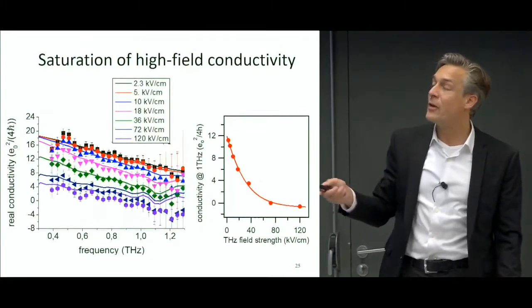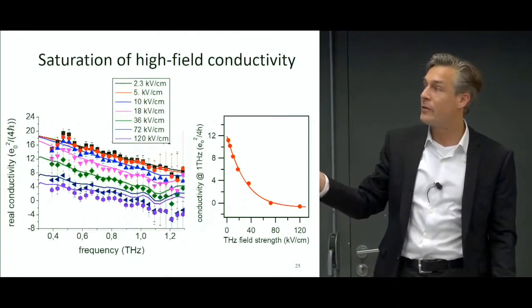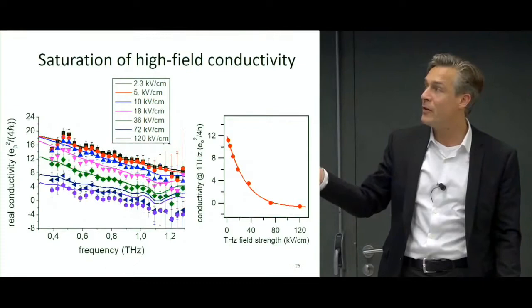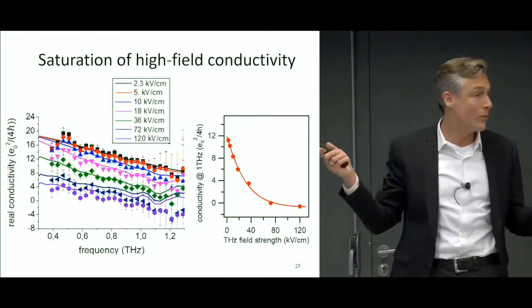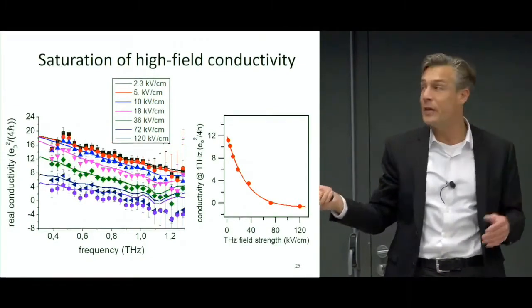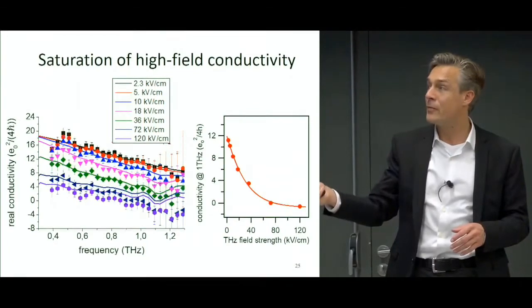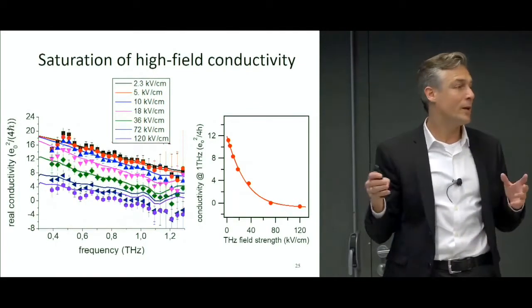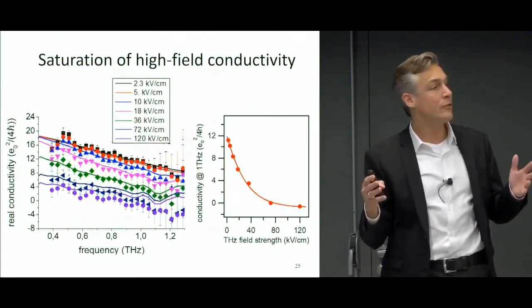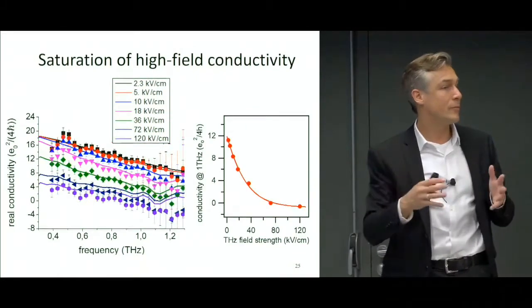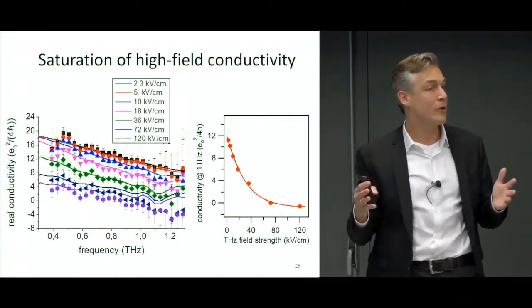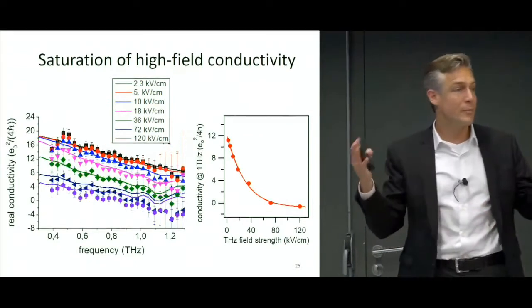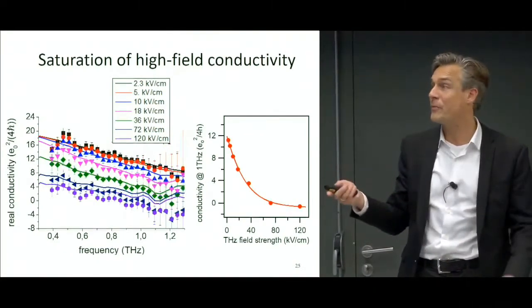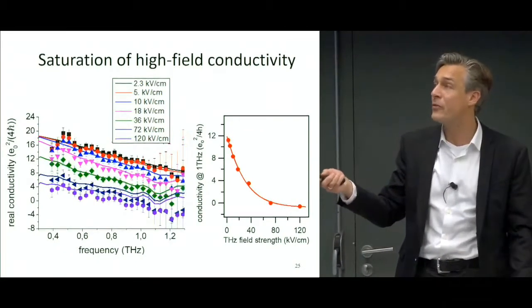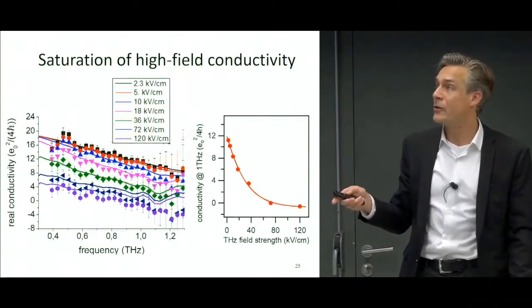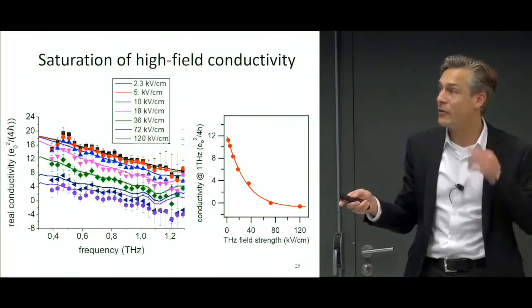And so as we go to even higher field strength, you can see that really the conductivity goes to zero, essentially. The conductivity at 1 terahertz. And so by applying these high fields, you can really kill these beautiful properties of graphene with moderate fields, in fact. So the high field conductivity actually saturates.